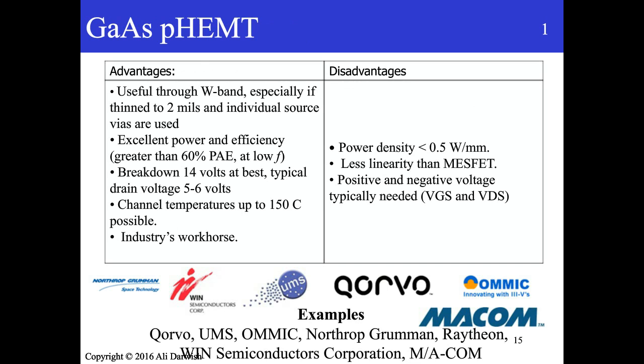So the GaAs PHEMT is really like the industry workhorse at this point. It's the least expensive. It offers good performance, very mature, and so on. Typically, the power densities we get out of gallium arsenide is perhaps limited to half a watt per millimeter, and the linearity that we get from the PHEMT is usually less than the MESFET.